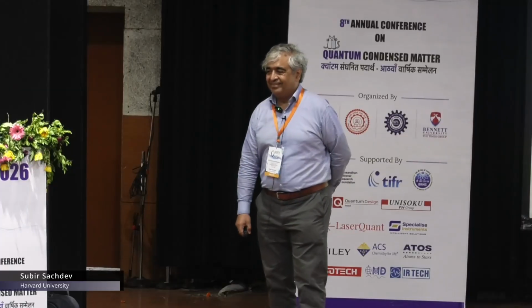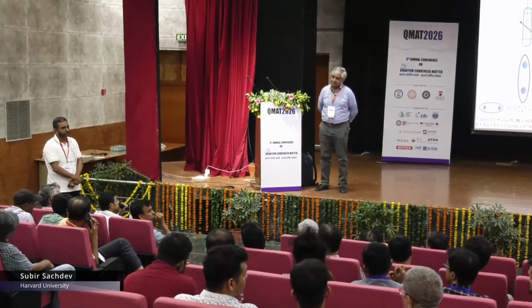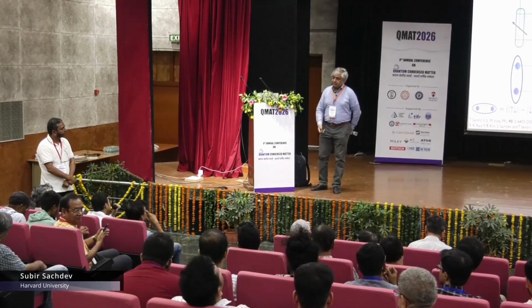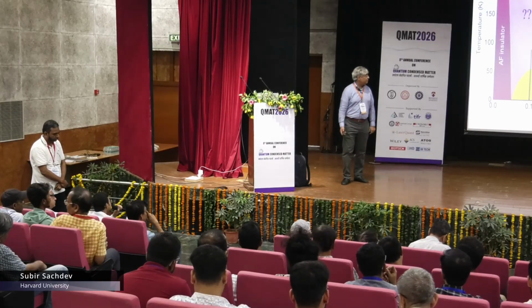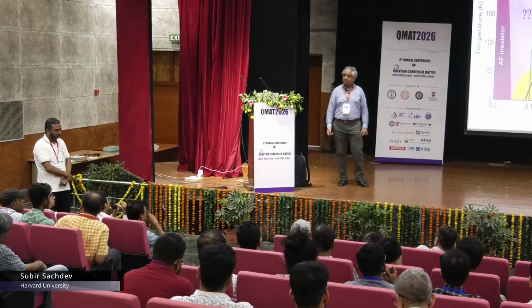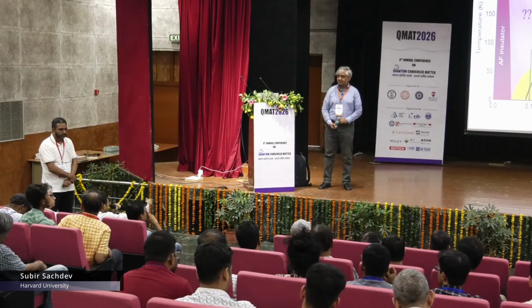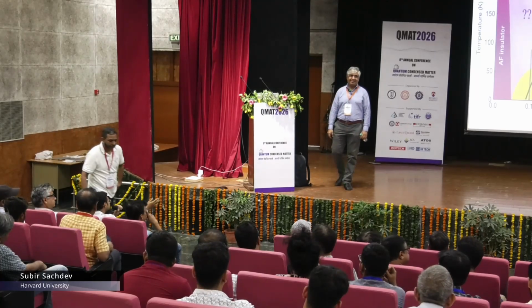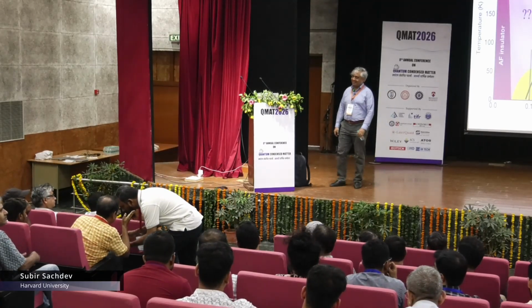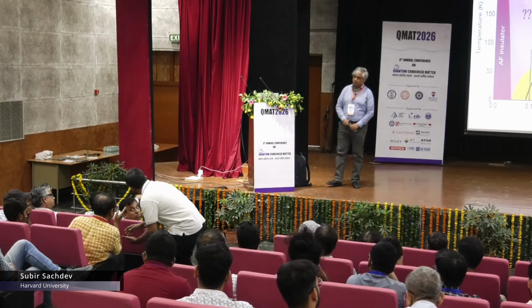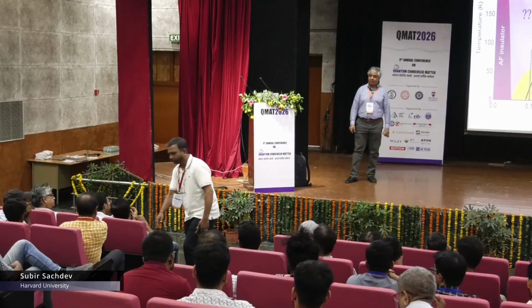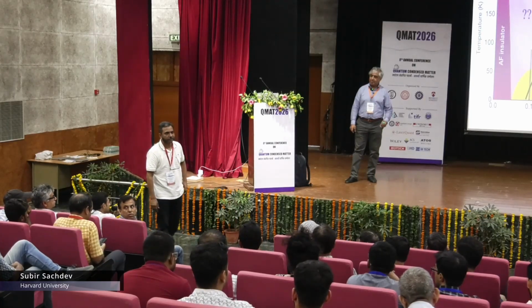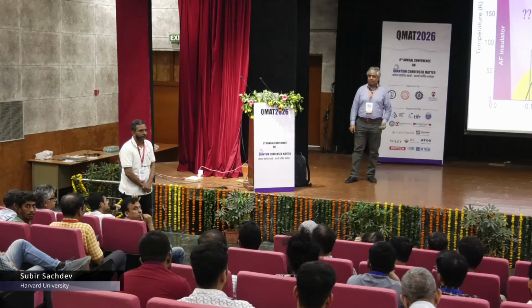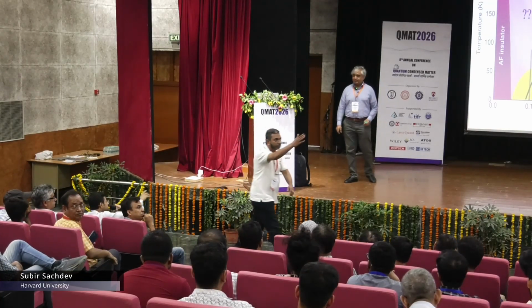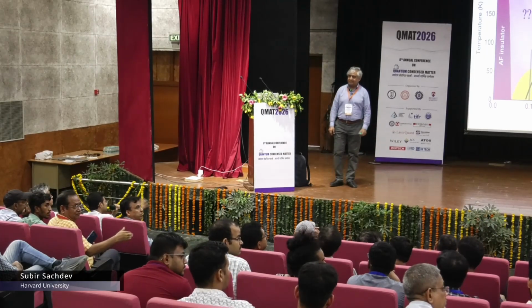And so, very inspiring talk as always. You alluded to this STM data on the normal state cores of the vortex lattice as being indicative of the normal state, and these density waves as being part of the normal state. You also alluded to the normal state being a FL star, and there is a transition. But in the experiments at very high fields, where you can kill the superconductivity to see the actual normal state, it was my reading of the experiment that they saw a glass as the starting point. What is missing in the experiments, that they don't see these density waves and FL stars that you think of as the starting point for this theory?